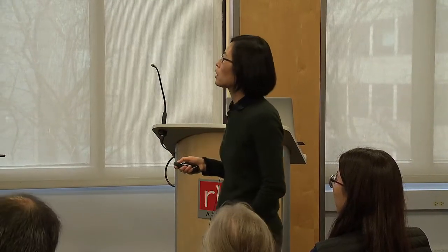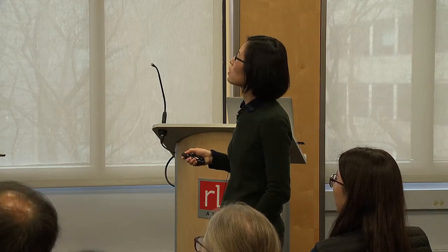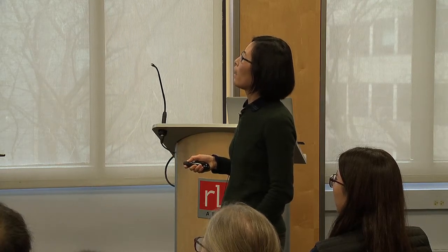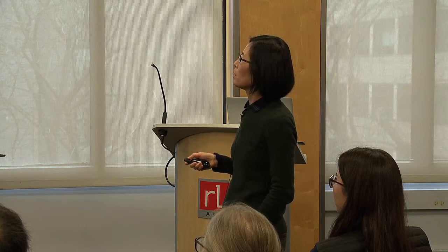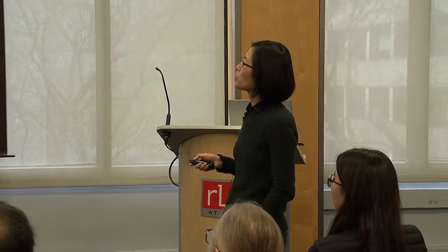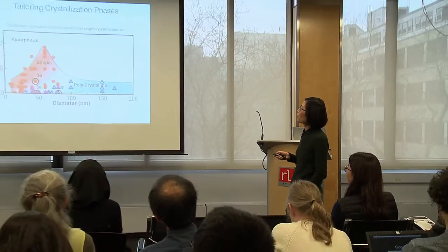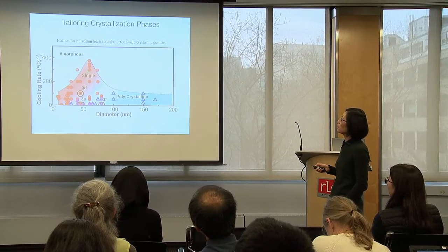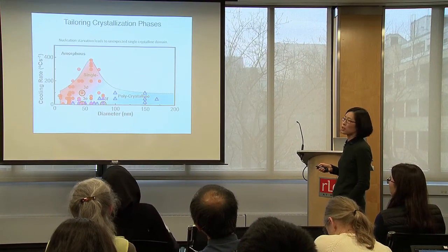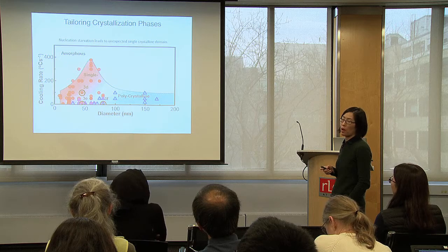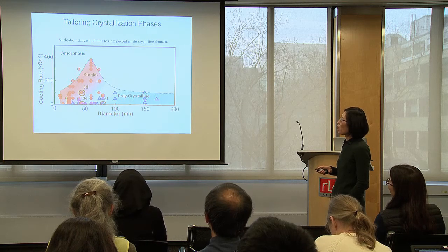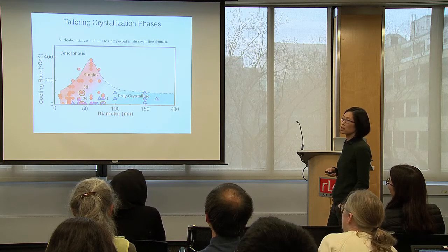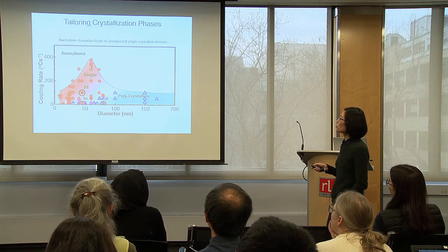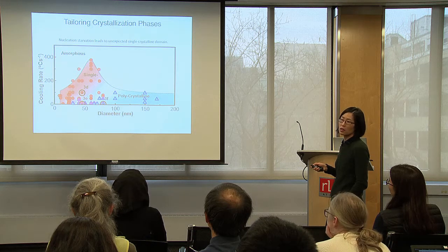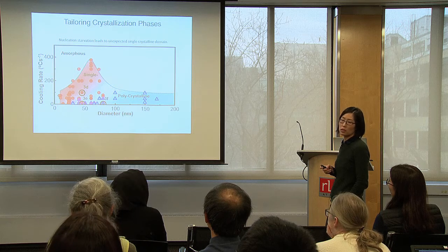So then we finished the phase diagram. So here was a critical cooling rate, the shape. And underneath, we know we can crystallize. We've sort of mapped out where the single crystallization can happen and where more expected polycrystalline phases will come out. So for small rods, because you don't have any nuclei, you will have a single crystallization event. If you also force the kinetics to be very fast, then you can also have a single crystallization event. Okay.